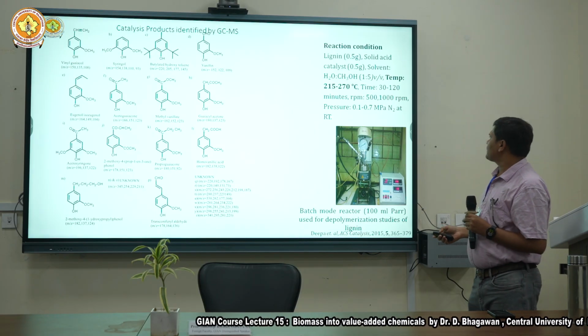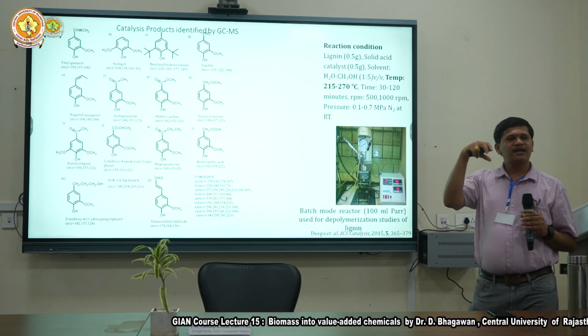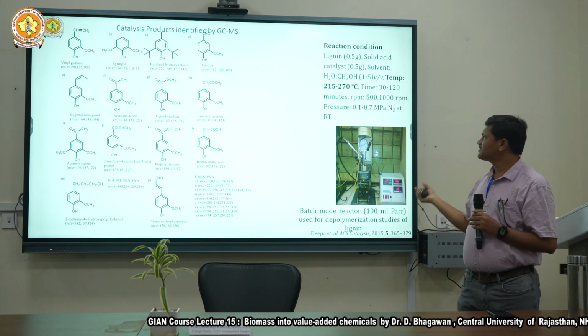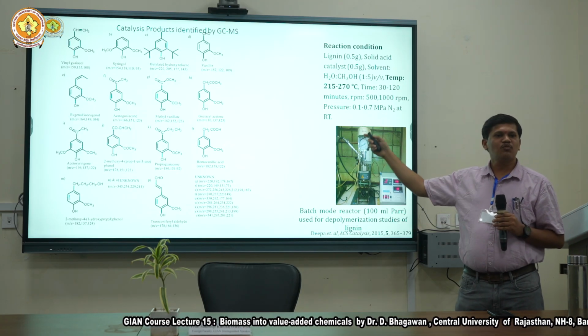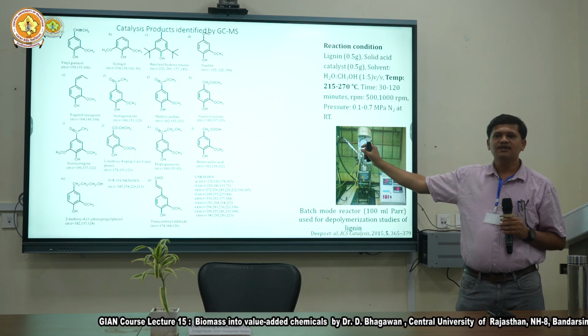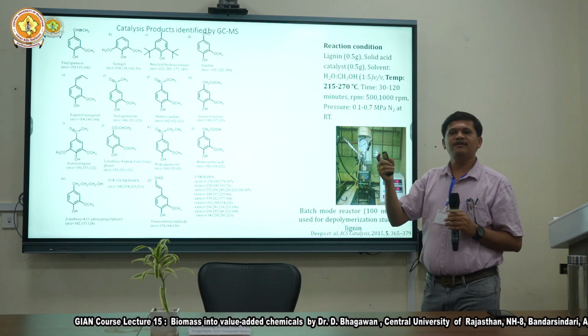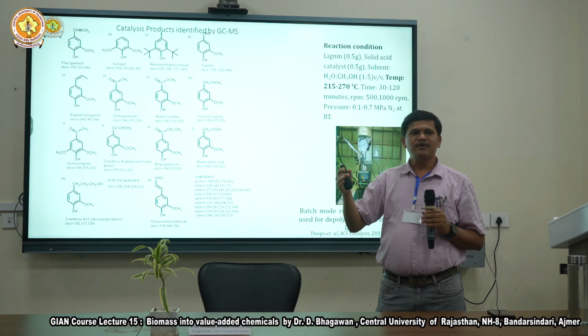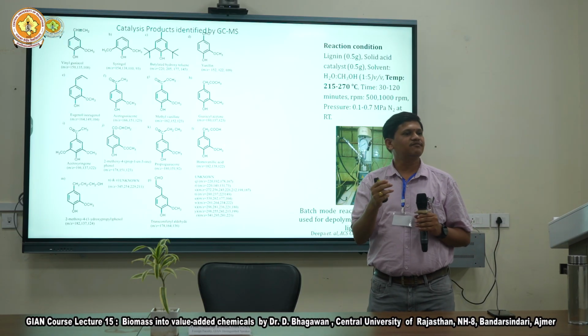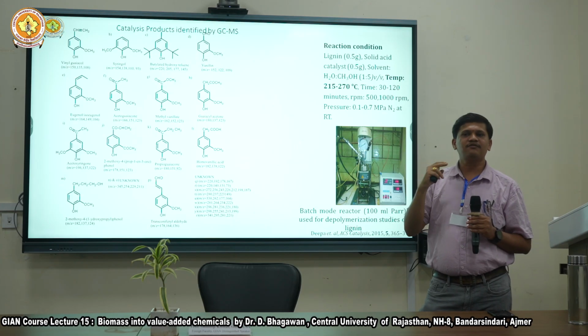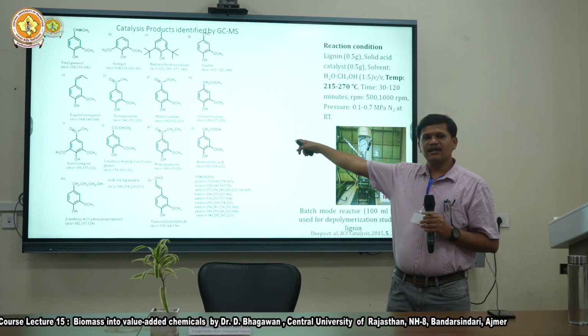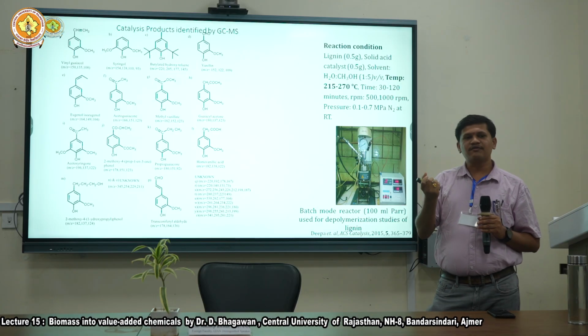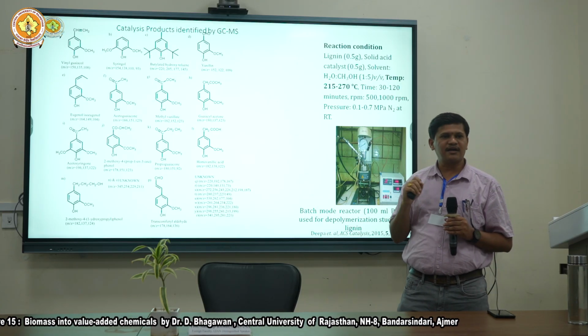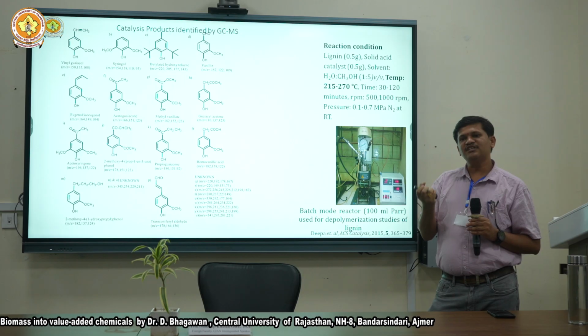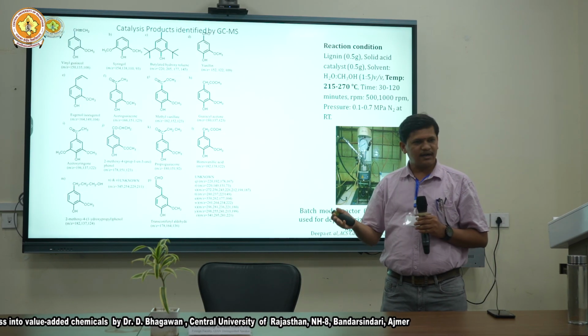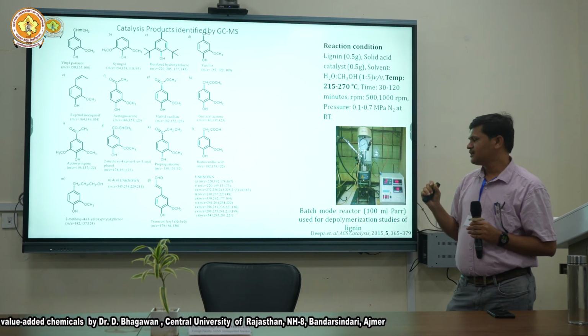And this is one of the reactors, at 215 degrees temperature under controlled, anoxic conditions, where they have converted it into all these monomeric components. So this is the real field sample. As I mentioned, whenever we go for a real field sample, we will get more products. Whichever catalyst or reactant we are using, it will break down wherever it wants to. And as I mentioned, the beta O4 linkage requires very little energy, so every beta O4 will get cut, and after that, if we have a bunch of electrons, then it is going to break down the other linkages present in our lignin.